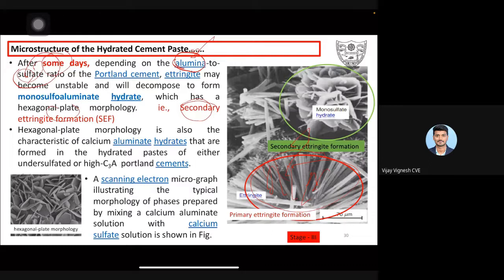Initially the primary ettringite formation is needle-like structures. After some days, the needles become like hexagonal plate structures. Plate-like, looks like the petals of a rose, like this. That's called a plate, right? The initially needle-like structures, after some days, become a hexagonal plate morphology. The hexagonal plate morphology is also a characteristic of calcium aluminate hydrates, CAH, which are formed in hydrated paste of high C3A Portland cement.